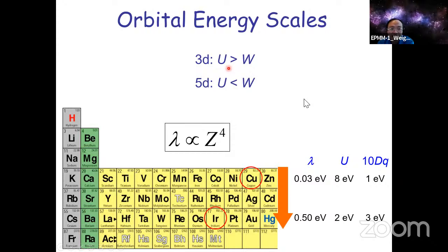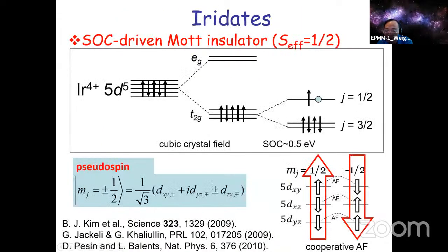Okay, Mott insulators, put in a simple way, occur when the local Coulomb interaction is larger than the bandwidth, so then we have Mott insulators. This does not in general hold in the 5D materials because of the more extended orbitals. However, spin orbital coupling is proportional to the fourth order of the atomic number. So in 5D atoms, it is pretty large compared with the local Coulomb interaction U and the crystal field splitting. So this could split the wide 5D band into a narrow band near the Fermi level, as shown in this